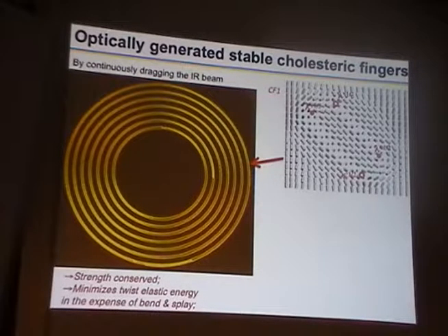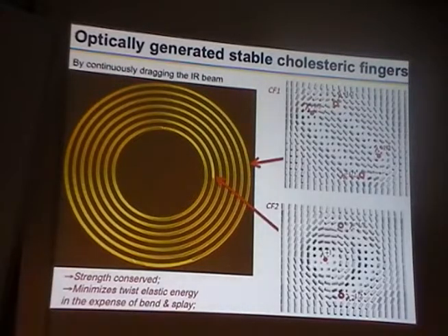The material wants to form a twisted configuration, but the boundary conditions don't let it do it, and so the initial black and here unwound homeotropic state is not necessarily energetically favorable, but by shining the laser light, we can relieve this frustration locally and draw such defect configurations, right? So in here, this is a quadrupole of disclinations.